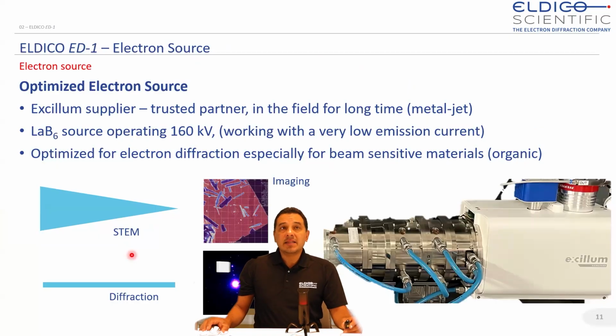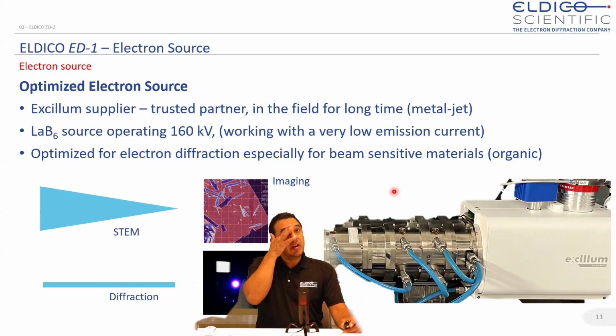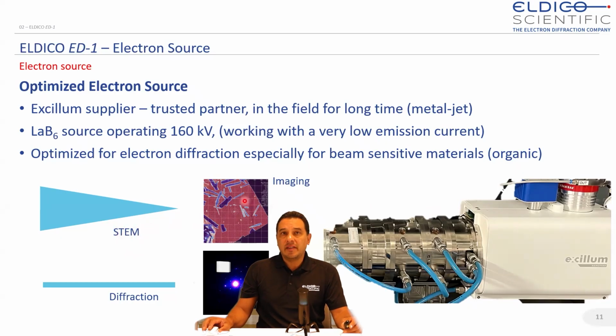So our beam has been optimized. Our supplier is Excillum, the supplier of the metal jet used in X-ray crystallography for many years. It's our trusted partner. We use a LaB6 source, which is operated at 160 kilo electron volts, and it has been optimized for the purpose of electron diffraction. We have two types of beams. We have the so-called STEM beam, which we use for imaging to identify our particles, and we have a very, very parallel diffraction beam. Some people have used our data exactly to test the parallelism of the diffraction beam, and they have told us that our beam is one of the most parallel beams, or the most parallel beam, that they have seen in the field of electron diffraction.